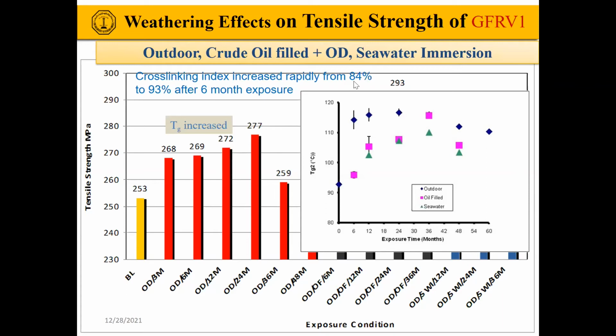When we received it, it was measured to be about 84%. After 6 months, it went up to 93%. So curing was happening under the sun of Dhahran. And after curing, let's say between 24 and 36 months, you can see that degradation starts to occur. But still, up to 48 months, we still have the tensile strength, which is higher than the baseline, which is the as received material.